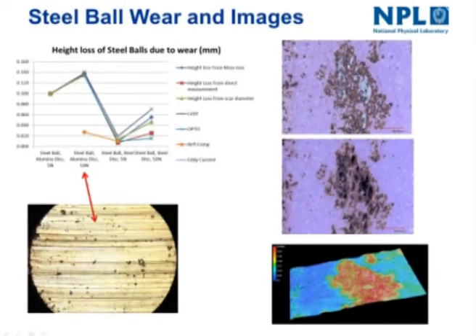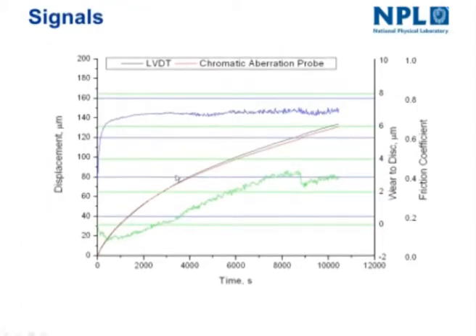And this shows some examples. We get build-up of material on the surface, as I've indicated earlier in this system, and if you look here, you can see that's this rust material again, and it shows a 3D optical micrograph of that surface. One of the advantages of this test system is the black line here is the LVDT. That measures the displacement of the pin into the disc. The chromatic aberration measures just the displacement of the disc. So by subtracting those two, you can get, for the first time almost, an independent measure of the wear of the pin and the disc.